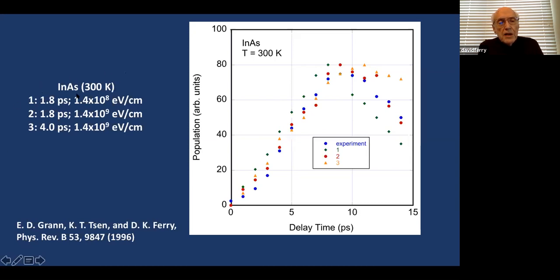So we have 1.8 picoseconds, 10 to the 8th, 1.8 picoseconds, 10 to the 9th, 4 picoseconds and 10 to the 9th. And we get a Goldilocks effect, right? If it's too small here, it comes up here, peaks a little early, and it falls off too rapidly below the experimental points. On the other hand, if we use 4 picoseconds and 10 to the 9th, we get the orange curve, which peaks too late and lays above the experiments. But if we use 1.8 and 10 to the 9th, just right. Just like Goldilocks said, it lays right over the experimental points. So that gives us some values for these things. Today we use a slightly smaller value, as I'll show you in the next slide.